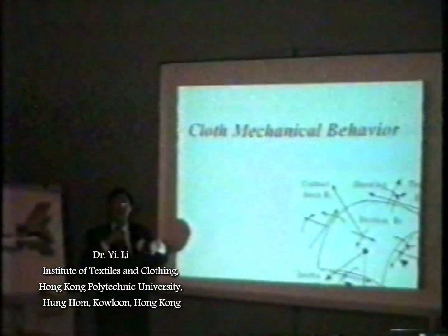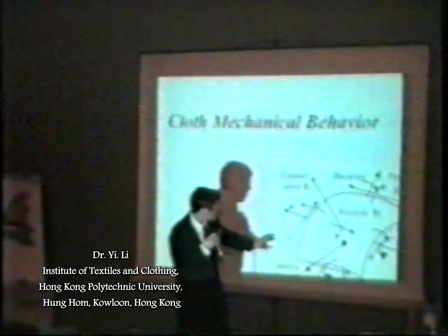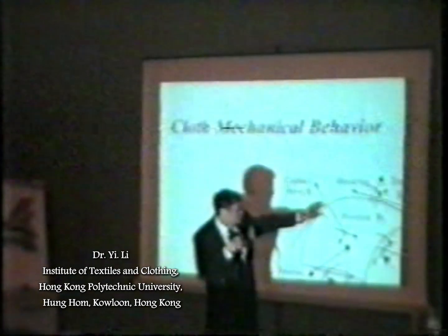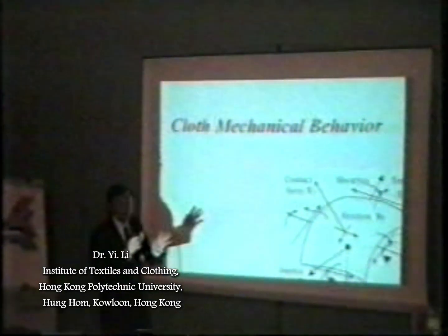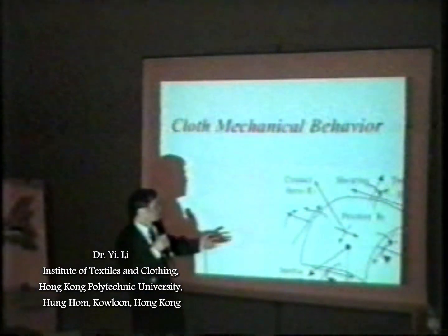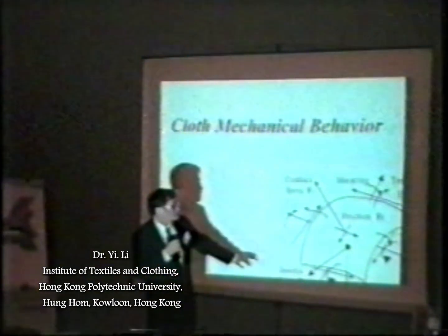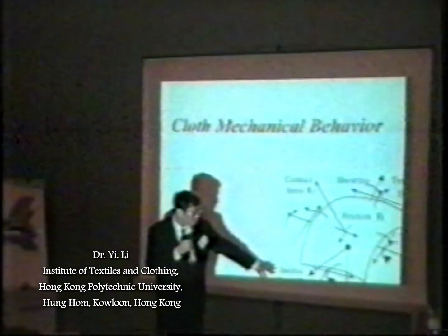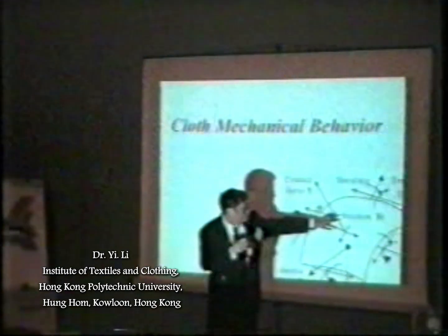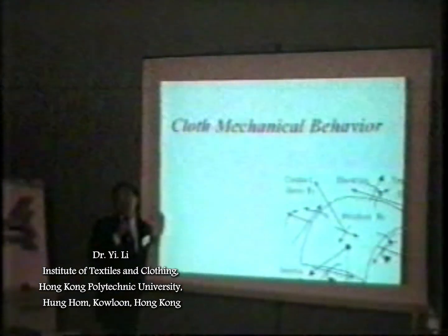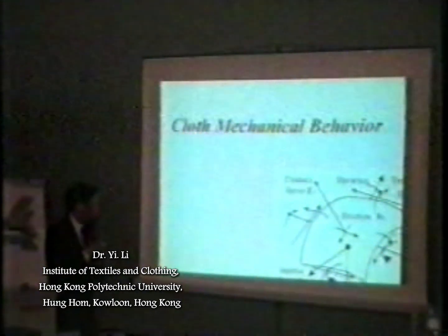In terms of the first analysis, the forces when we wear the garment include the internal forces in terms of shearing, tension, compression, bending, and so on. Meanwhile, there is a contact force from the body to the garment, also the inertial force of the mass of the garments as gravity, the frictional forces between the garments, and the internal frictional forces between the fibers and yarns.